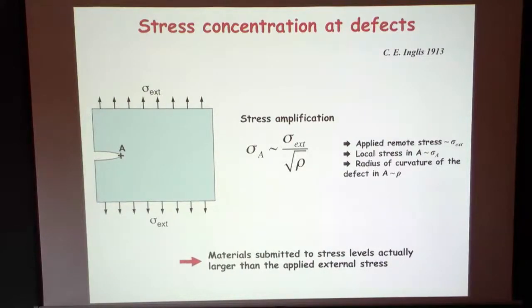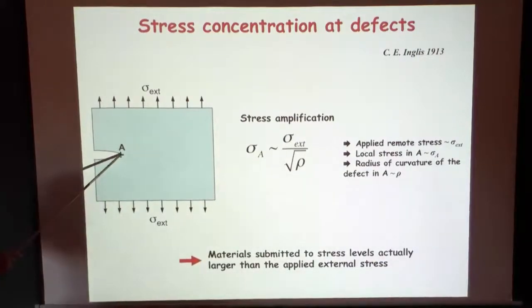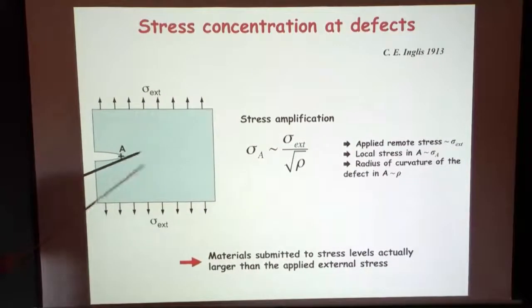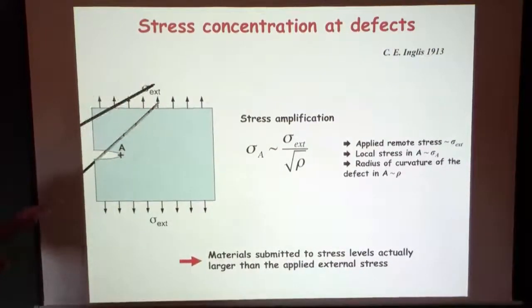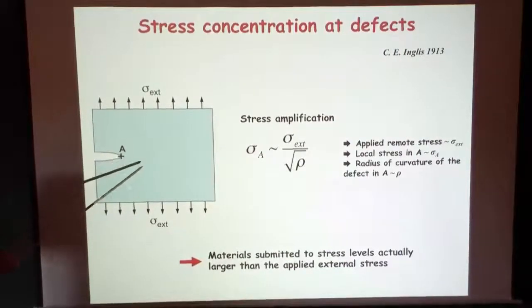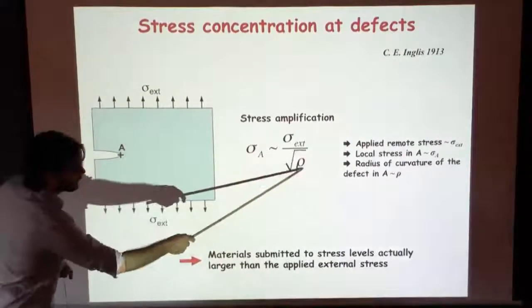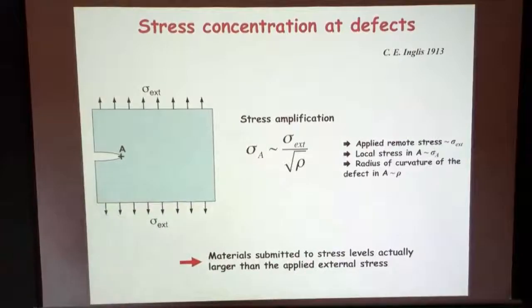Obviously, for r going to large scales, this goes away, and the other terms become dominant. So you recover the external stress that you're applying. But at the scale of A... Let's say that if you move from A to a distance of the order of the radius of curvature, you recover the stress. Yeah, I'm looking really at the tip. But that's it. The length scale you talk about is provided here by rho.